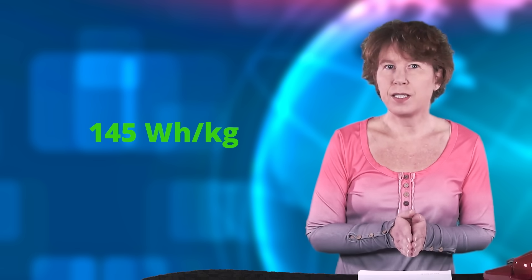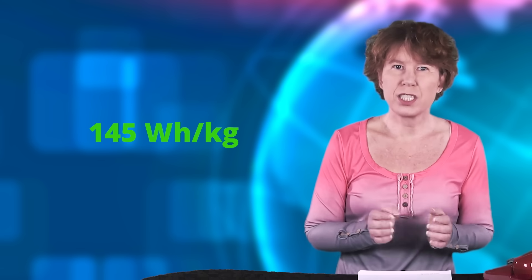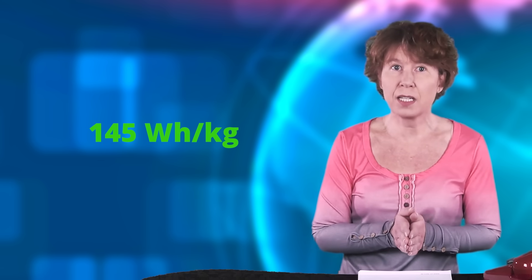First of all, they quote an energy density of 145 watt-hours per kilogram, which isn't bad but about half of that of current lithium-ion batteries. Then there's the question how robust such a battery is and how well it copes with different temperatures.